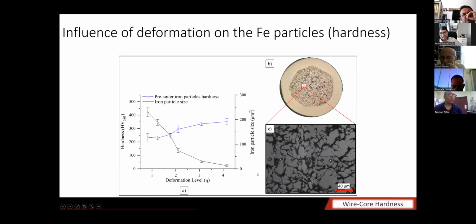So we did a hardness analysis scan on the core of the material before the synthesis of the wires. We see that increasing the deformation levels causes a slight increase in the hardness of the iron particles, if you see here. And the average size of the iron particles is reduced like this. The area in micrometer square of each particle is reduced as the deformation level increases. This allows us to quantitatively explain how the size of the iron particle is reduced.